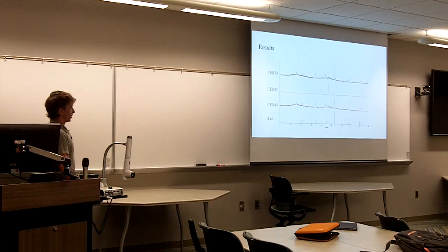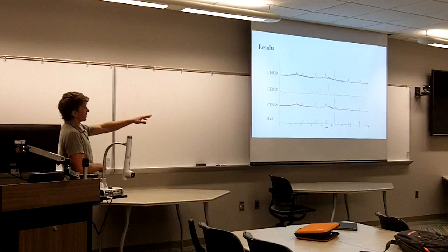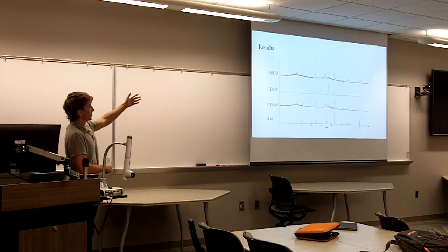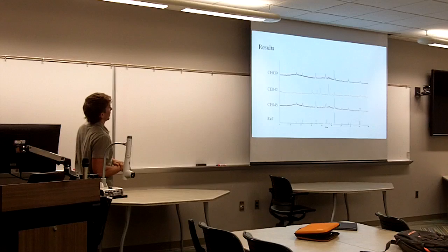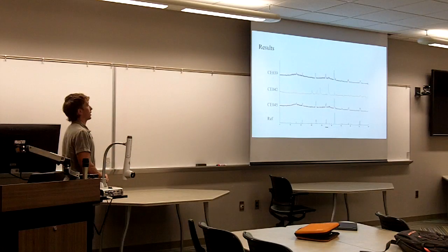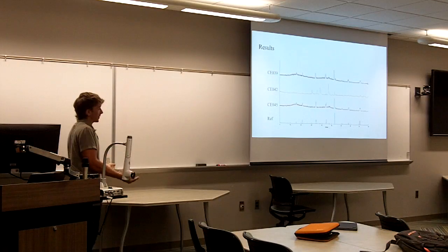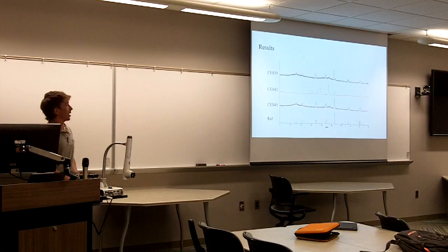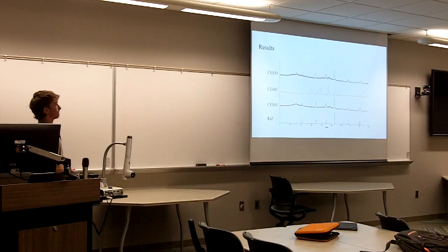And then these were our other three CBBs that we made, with the reference being at the bottom. And as you can see, some of these samples, like 42, don't align with every single peak, while others, like the 45, have more consistency with the peaks shown in the reference. And that could be for different reasons of impurities or other things, or CBB not actually being made but looking similar. So you have to line up the peaks and judge whether it's similar enough.